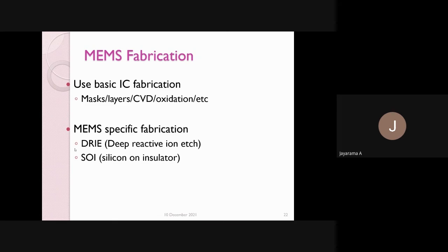Typically with high aspect ratios. In DRIE, the substrate is placed inside a reactor and several gases are introduced. A plasma is struck into the gas mixture, which breaks the gas molecules into ions. The ions are accelerated towards and react with the surface of the material being etched, forming another gaseous element. This is known as the chemical part of reactive ion etching.